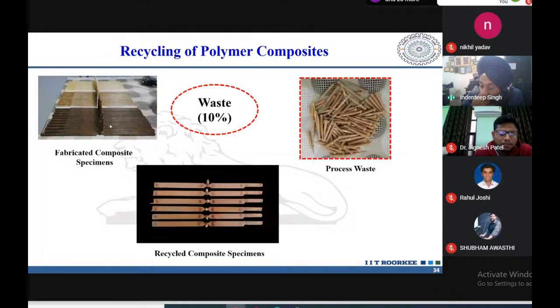Now, this is another important aspect that we are touching upon, the recycling of polymer composites. These are the samples, as I told you, that as per our mold, we get these three samples in a single shot. So there are a number of samples that you see here. This is the tensile testing sample. We will cut it from here and we will get one tensile testing sample. Then this is a flexural testing sample, and finally we have an impact testing sample. So we use different samples for different types of characterization.